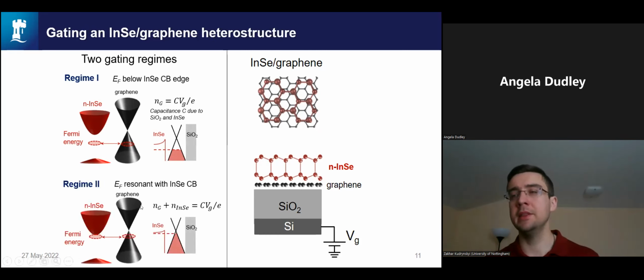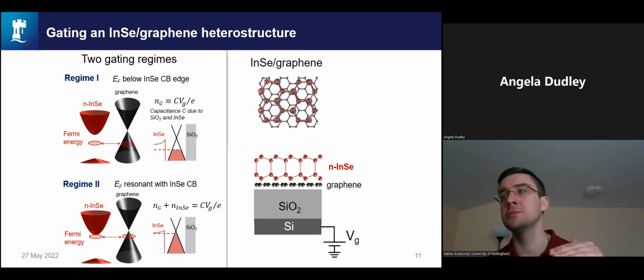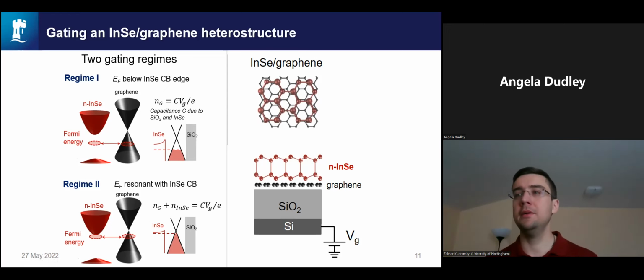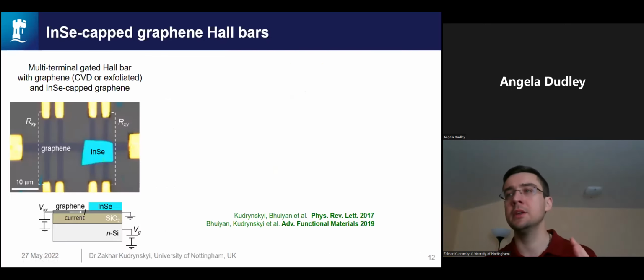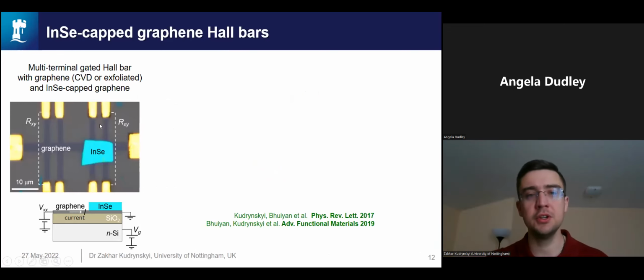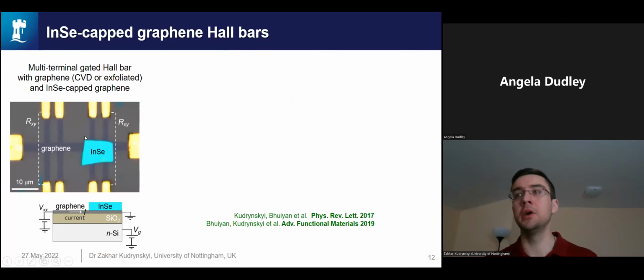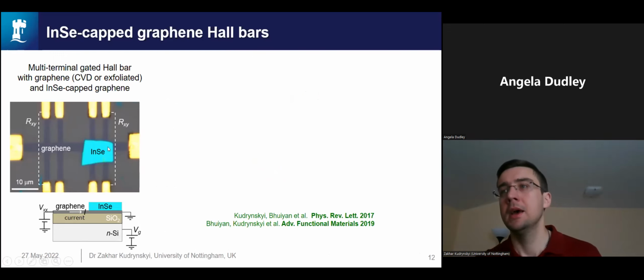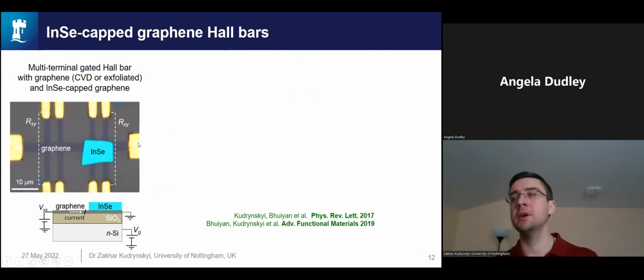And then you go to another regime, which is more interesting, when the Fermi level starts approaching either donor states or the high density states in the conduction band of indium selenide. This regime is where you have charge redistribution between the two layers. So we started electrostatic gating in this type of structures. These are Hall bars made of CVD or exfoliated graphene. Part of the Hall bar is covered with an indium selenide flake. The two parts of the device are in series resistance configuration, so we can pass the same current and look at longitudinal resistance and Hall resistance.